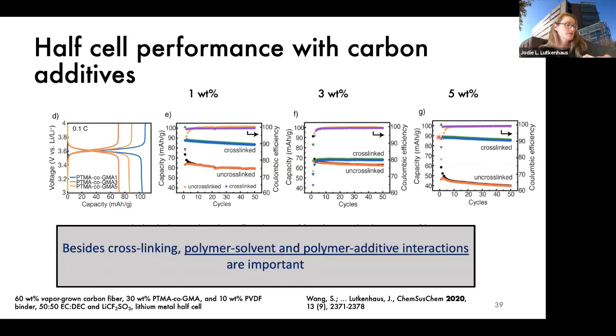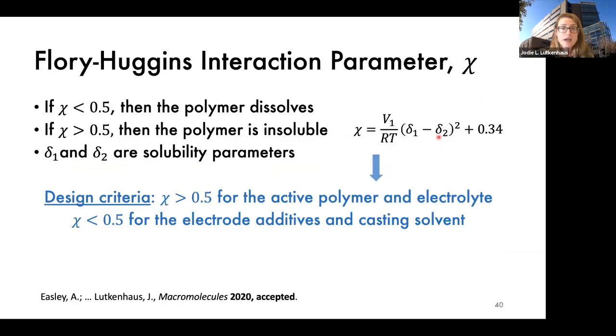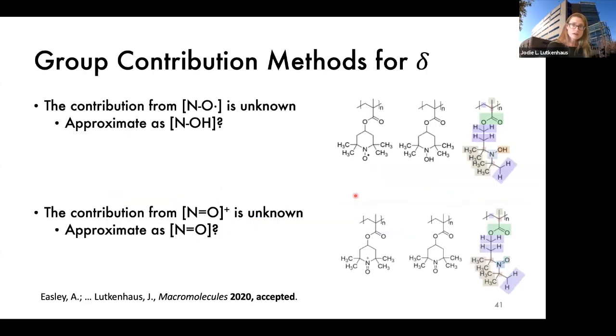Okay, so besides cross-linking, polymer-solvent and polymer-additive interactions are really important. I thought, oh, we can solve this problem by just selecting the right solvent. But when you get into it, there really isn't any knowledge of Flory-Huggins interaction parameters, to my knowledge, for PTMA. So that presented the problem that we needed to identify solubility parameters so that we can begin to estimate whether or not these polymers were going to dissolve. Sometimes you want the polymer to dissolve, like when you're trying to cast it to produce the electrode. In another case, you don't want it to dissolve, as in battery operation. If you try to do group contribution, at least to my knowledge, there's not a group contribution for the nitroxide radical or the oxoammonium cation.